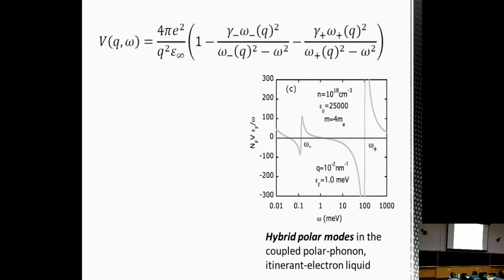So instead of now having a system of polar phonons and electron plasmons, because the two are strongly coupled, the correct degrees of freedom that you actually measure in experiments look like this, and they're actually hybrid polar modes. And we think that these are the modes which are the predominant pairing mechanism for the electrons in strontium titanate.